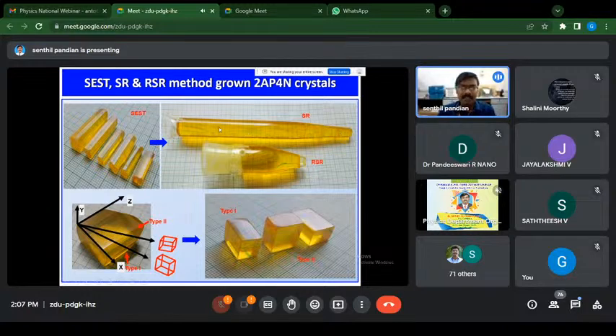The problem in this SR, Sankaranarayanan Ramasamy method, is that even when we have used a lot of recrystallization process, and we have poured the saturated solution and grown the crystal, still a lot of impurities appear in this solution. So we cannot avoid them in this solution grown crystal. When we grow the crystal by this SR method, the impurities are pushed from this glass sample. At a particular time, we cannot control the impurity segregation. So once it exceeds a limit, the crystal will stop growing. The multinucleation, milky opaque kind of thing will form at the top of this SR glass sample.